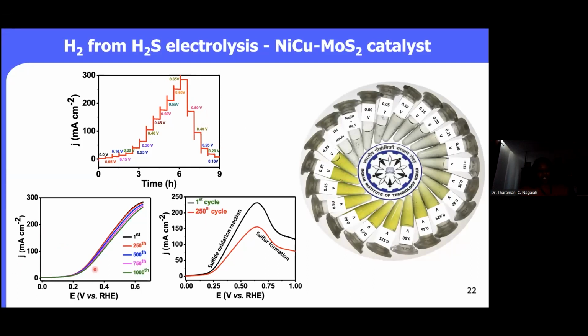Again, we perform the linear sweep voltammetry up to 1000 cycles. You can see that up to 500 cycles, we did not see any decay in the potential or even in the current here. However, there is a small decay after the 750th cycle, but considering the stability and especially the sulfur accumulation, this is quite commendable.